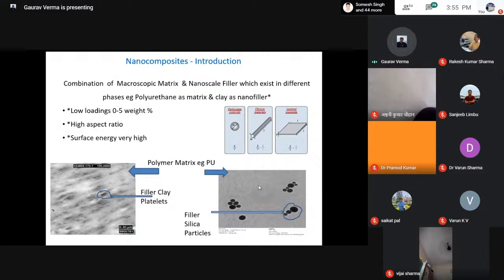Because many times you believe that if you just mix any matrix with an aggregate or a powdered nanomaterial, which does not have the requisite surface to volume ratio, or does not maintain that percentage, or the same aspect ratio, you will still be able to get the requisite results. It does not happen. It might happen by hit and trial, or you get results which are inconsistent.